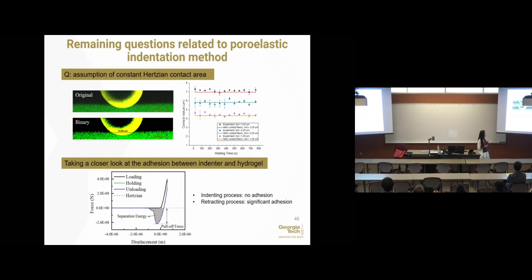But the story doesn't end there. When we look at this problem, it's more interesting than that. We apply displacement, compress it in, measure this force, and hold it there for a certain time so it relaxes. During this loading period, you see this fits the Hertzian no-adhesion solution very well. And the contact radius during holding time does not change. So adhesion doesn't play a role in this relaxation force measurement process.